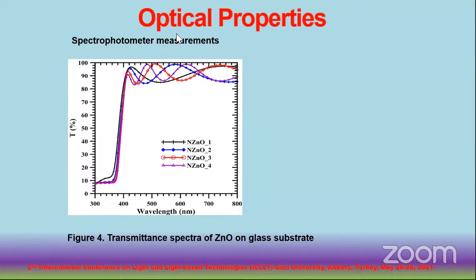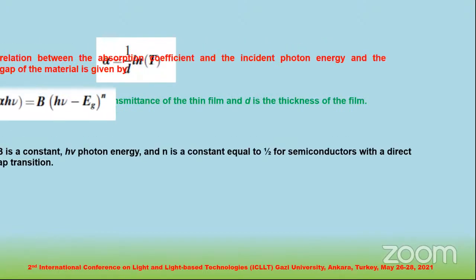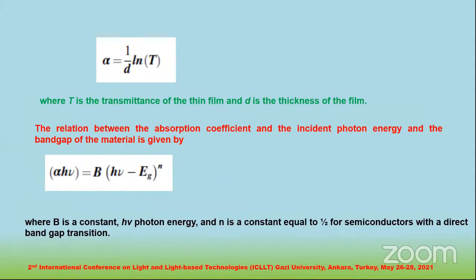Figure 4 presents the optical transmittance in the wavelength range of 300 to 800 nanometers for the films. It has been observed that as the thickness increases, the interference fringes increase. Further investigation about the energy band gap values was made taking into consideration the absorption measurements. Absorption was converted into the absorption coefficient by the well-known Beer-Lambert law as given below, where T is the transmittance of the thin film and D is the thickness of the film.